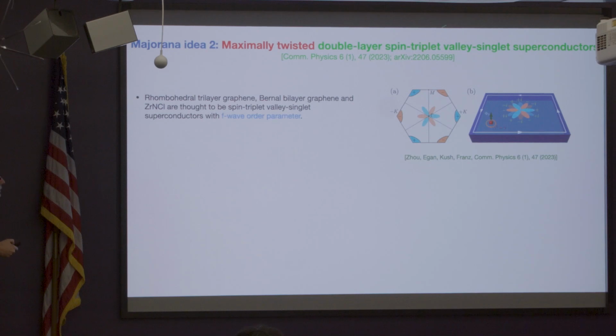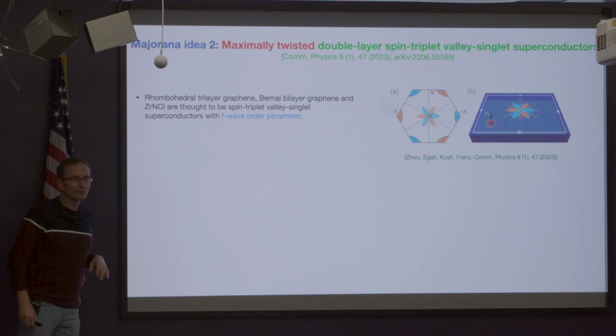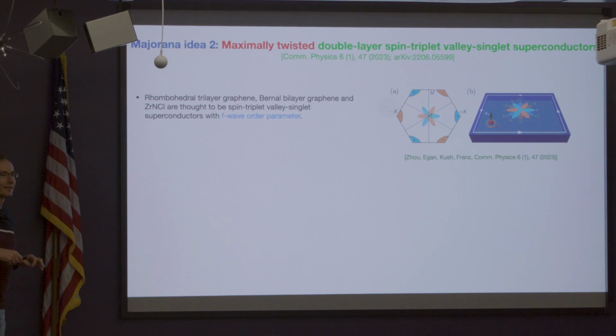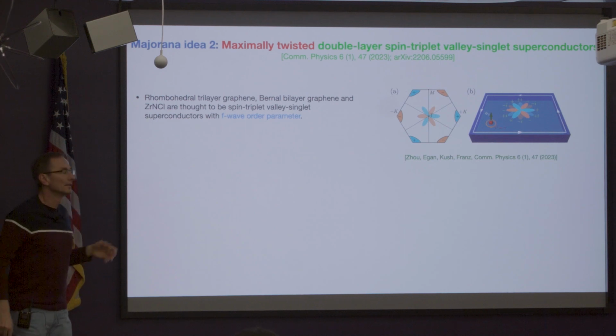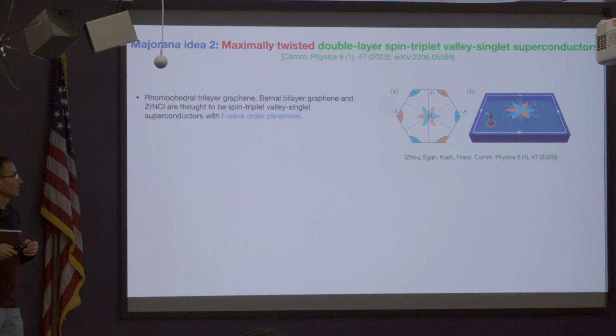Now, if you look at a topology of this, even though this is spin triplet F-wave, it's topologically trivial. It's fully gapped, but topologically trivial. It's fully gapped because even though this order parameter has nodes, they never intersect these small Fermi surfaces. So that's why it's fully gapped. And initially we thought, could this be topological actually? But if you look into the big table of tenfold way, you find that actually in this class, I forgot which class this is, but this has spinless time reversal symmetry and charge conjugation symmetry. You find that that class is actually empty in 2 dimensions. There's no possibility of topological phases.